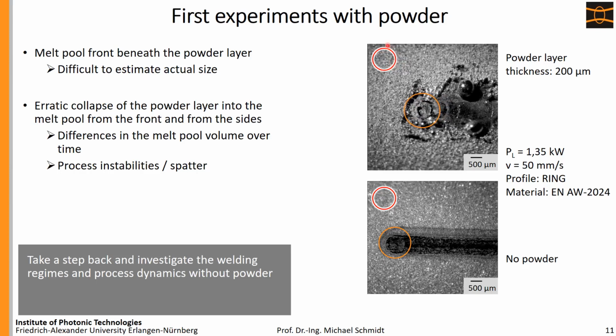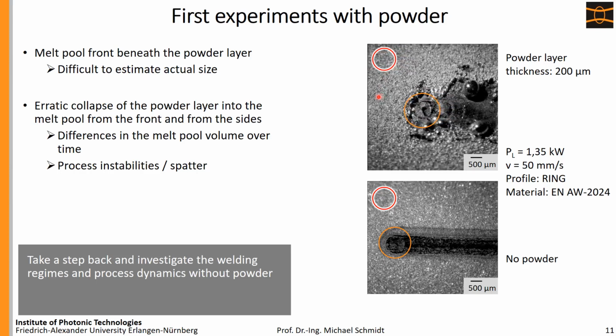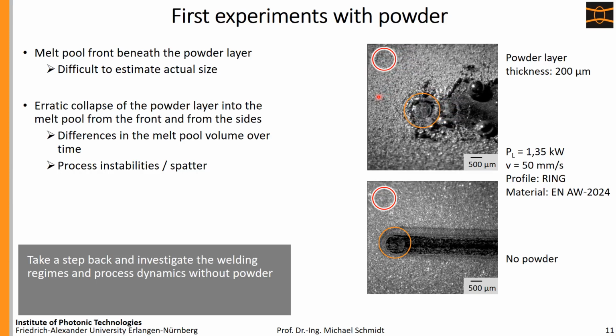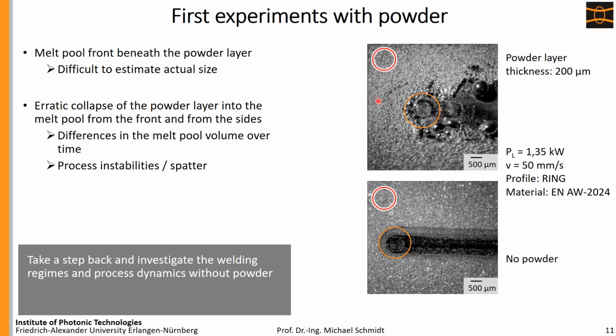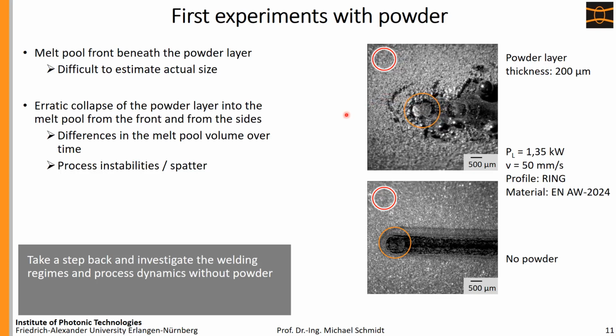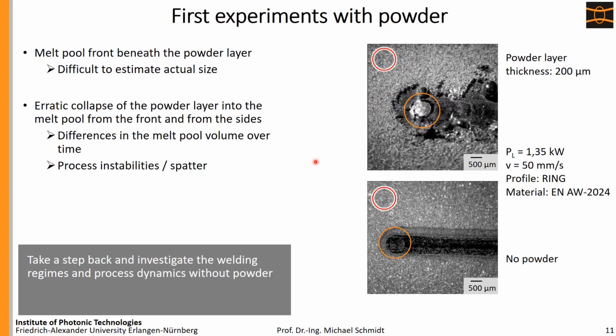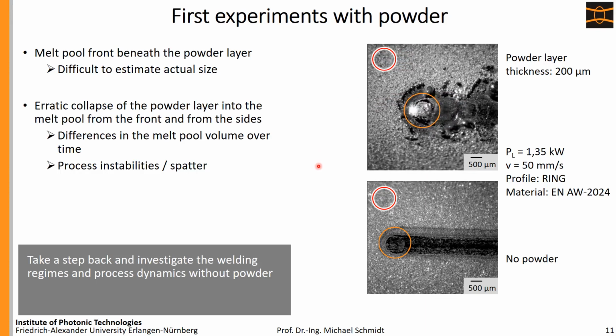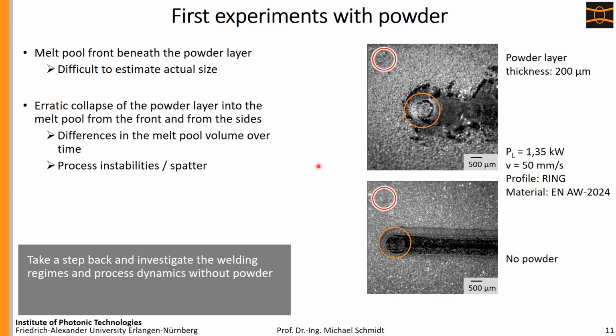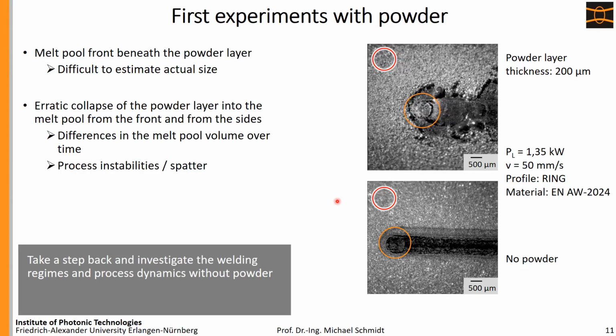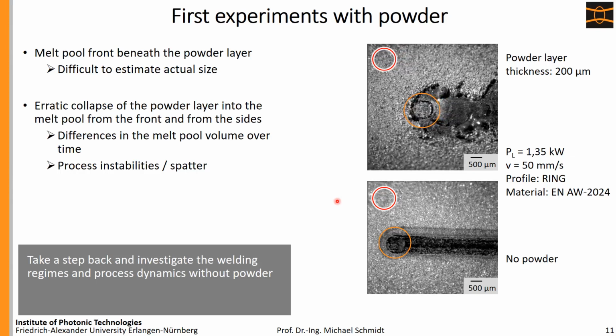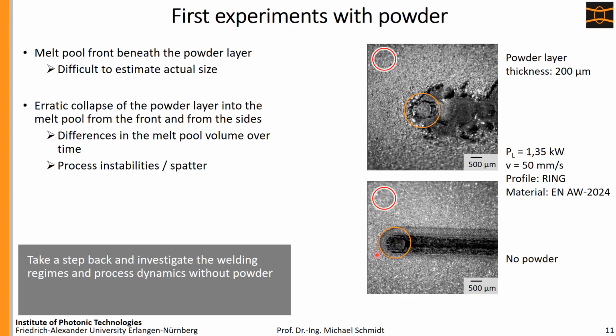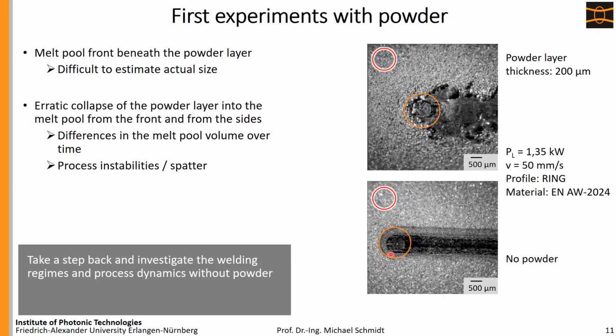By the way, this is the ring shape, as you can see here from the picture in the upper left image of the high-speed video. So what we did then is to see the first, let's say, process change in the laser material interaction. We didn't use powder, we just used a pure metal plate, and you can see what's going on here. Again, with a ring shape.